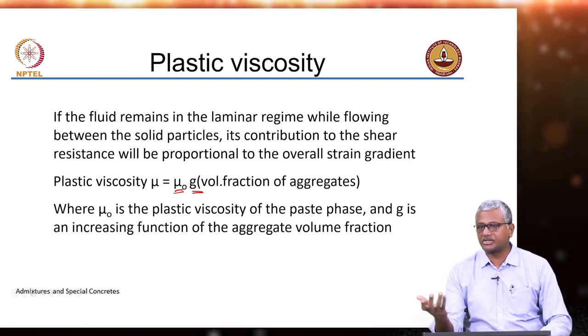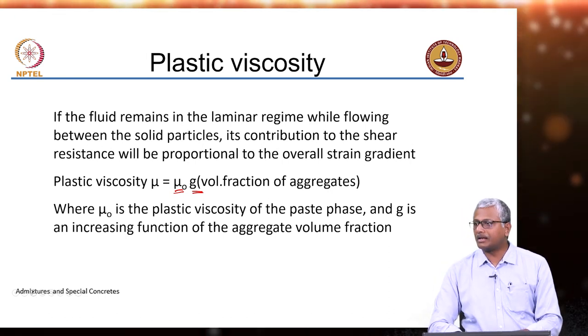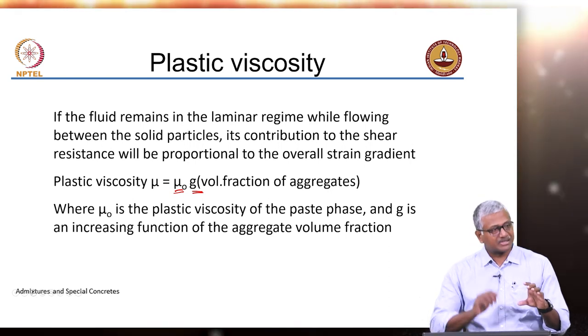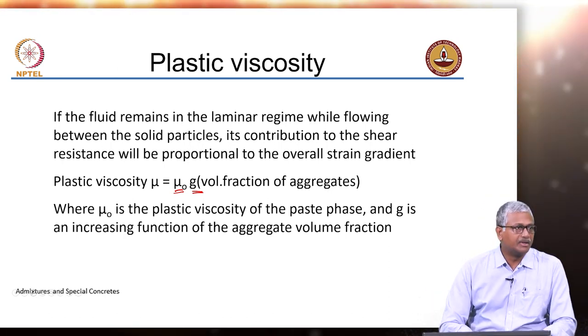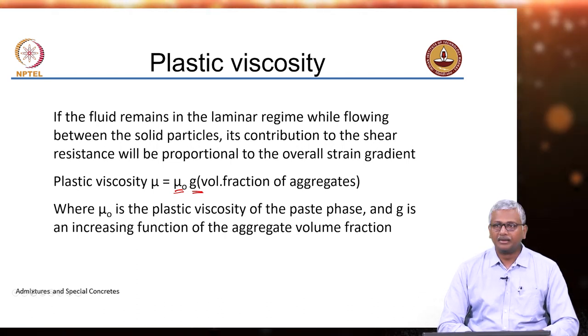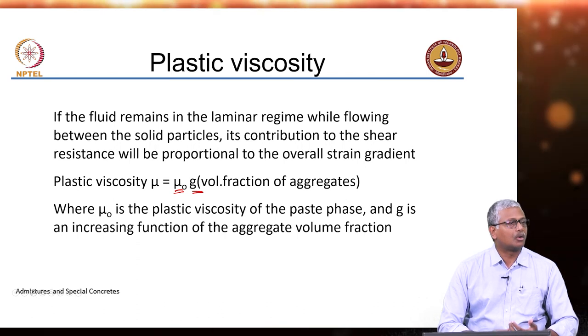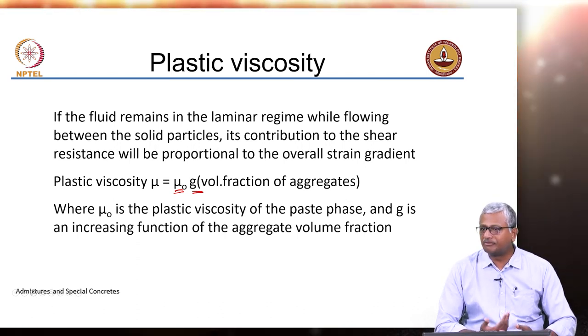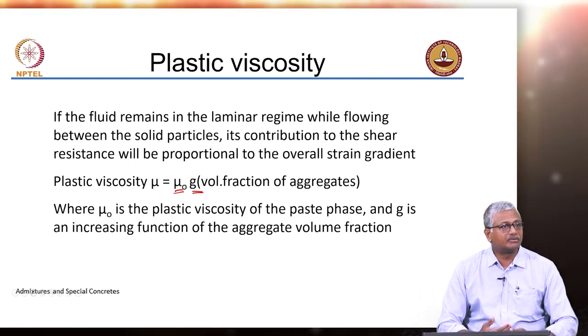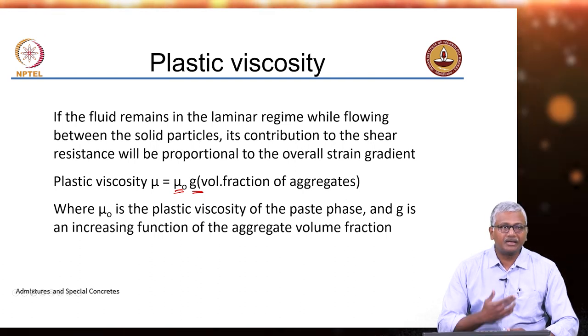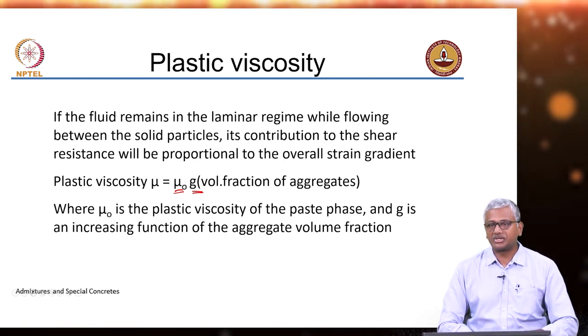This is very important when you think of an application like pumping — we are applying pressure to push concrete through a long pipe. Frictional forces restrict the amount of concrete that can be pumped. A concrete with low viscosity will carry itself quite easily through the pump. Pump blockages typically happen when concrete loses its slump or becomes stiffened due to delay in pumping, or because pumping heights are too great — pumping across very long distances generates heat while pressurizing the concrete.